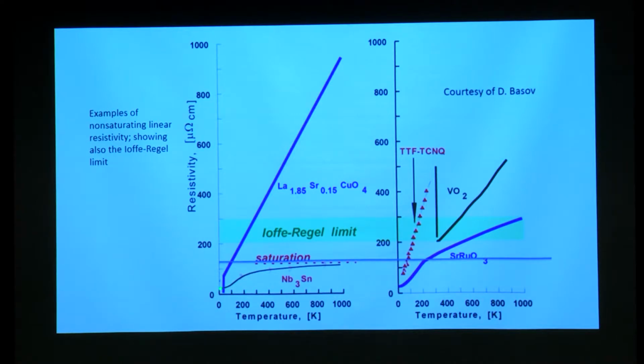So it's a very strange thing. By comparison, the resistivity of a very dirty metal, niobium-3 tin, increases linearly and then shows signs of saturation. So I have shown here a number of other examples: TTF-TCNQ, vanadium dioxide, strontium ruthenate. In all of these, the electrical resistivity increases linearly and happily crosses the Mott-Ioffe-Regel limit.